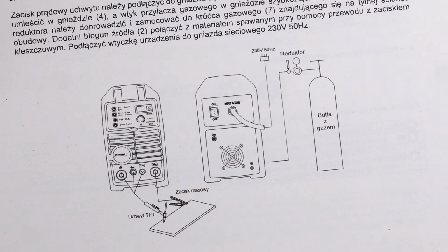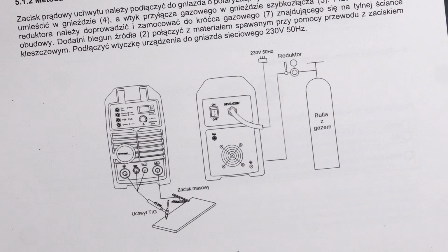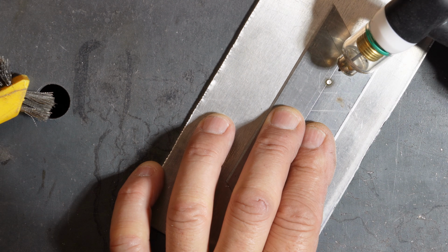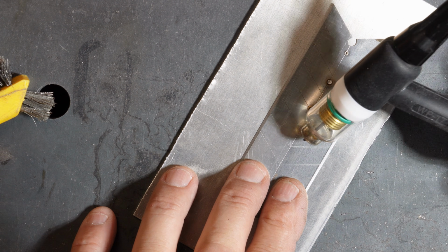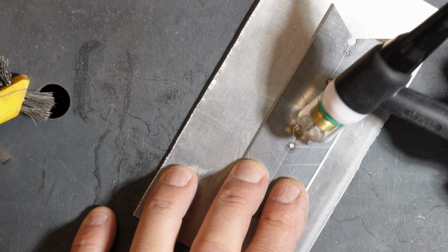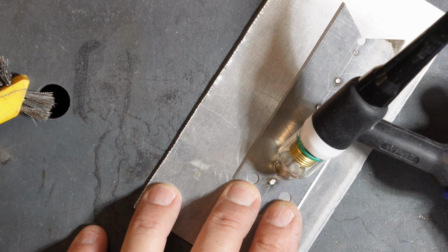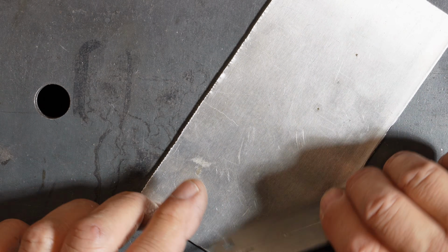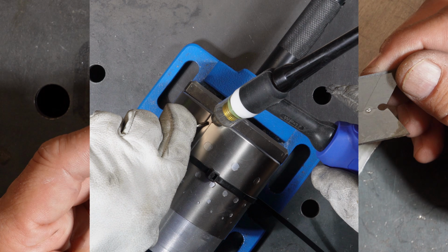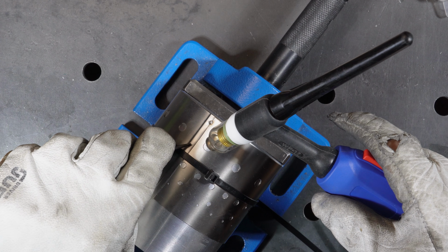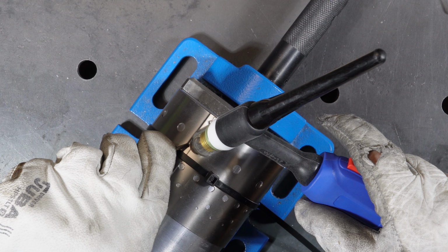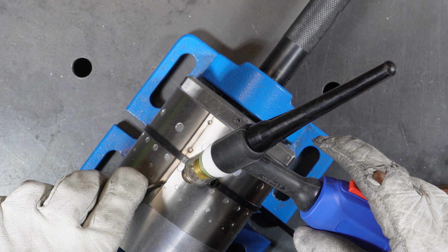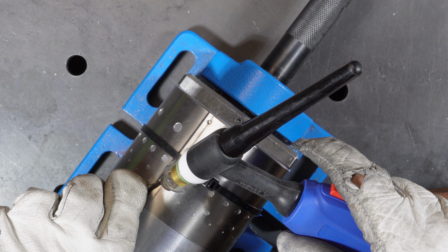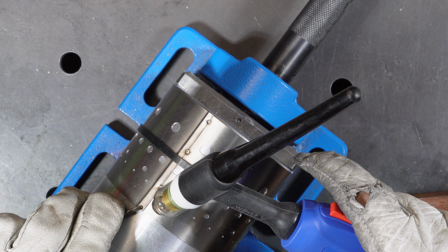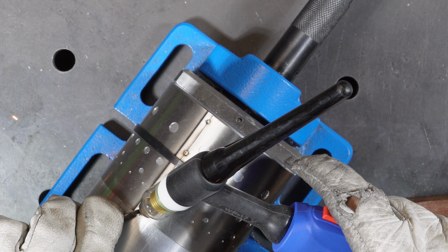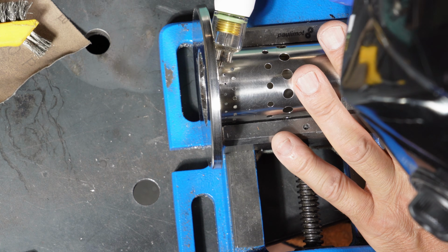The welder allows pulse durations as low as 30 milliseconds and currents down to only 10 amps. For my first experiment, I weld together two utility knife blades using 30 milliseconds and 80 amps. The result is surprisingly good and gives me confidence to continue. I then move on to the outer liner, using 30 milliseconds and approximately 60 amps. The inner liner and front end cap are welded using the same technique. So far, the results are very encouraging.